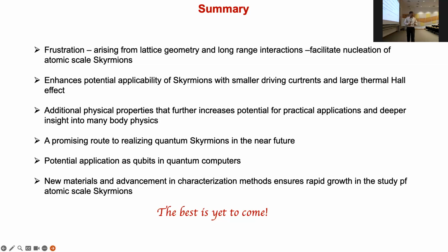So what happens is that you have a large degeneracy of low energy states, and that is geometric frustration. Then what is interaction frustration? Interaction frustration just means that even for, let's say, a square lattice that does not have geometric frustration, you have nearest neighbor interaction being ferromagnetic and next nearest neighbor being antiferromagnetic, just as we considered here.